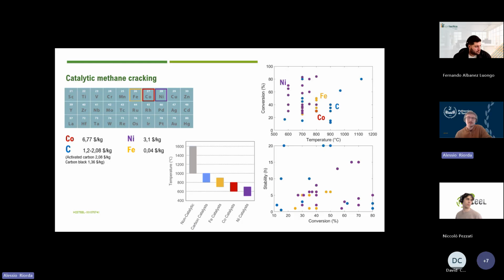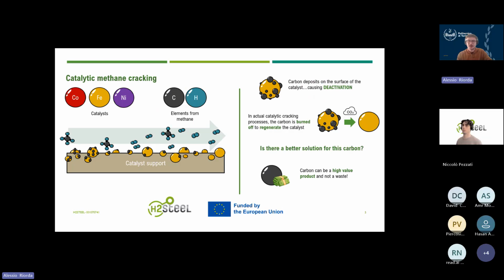In the other two graphs that you can see here, that represented the conversion dependent on the temperature and also the stability of the catalyst. This is another good point that we will discuss in the next slide. Why? Because, as I said, the reaction is breaking the methane into gaseous hydrogen and solid carbon. And the solid carbon has to go somewhere. In this case, if you are doing a catalytic reaction, the solid carbon is depositing on the catalyst. And this is the process that leads to the deactivation of the catalyst.